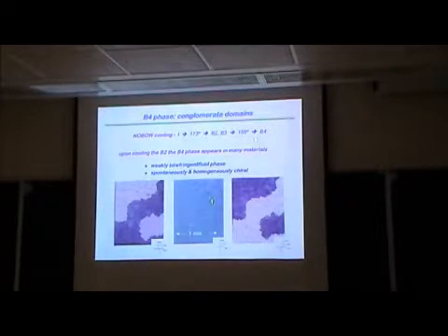And then once it gets into the B4 phase, it looks like this, and you can cool it to room temperature. Actually, the cracks appear as you cool into this lower temperature phase. Anyway, it looks in the microscope like it has this nice blue color between cross-polarizer and analyzer.